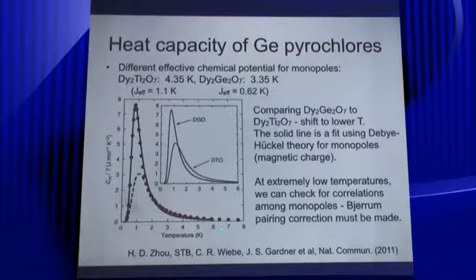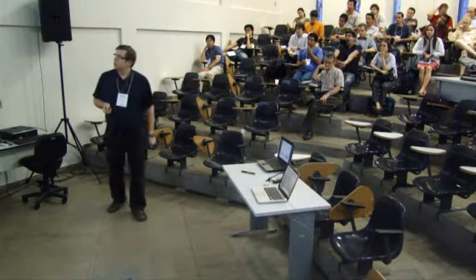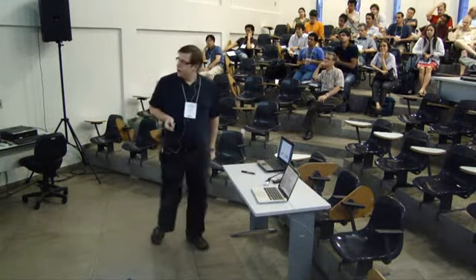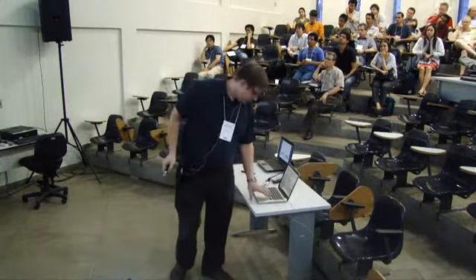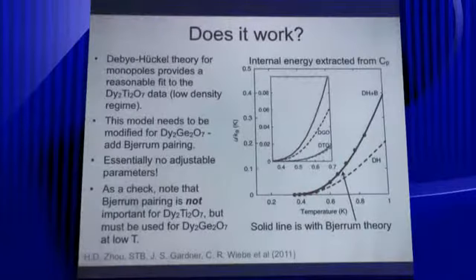And this is a fit that we've done to the Debye-Hückel theory with the chemical potential. So the chemical potential is smaller than you have for dysprosium titanate, which is the reason why you have many more monopoles at low temperatures. So what we decided to do was look at the heat capacity at lower temperatures, because as the monopole density becomes really high, you should have significant corrections for Bjerrum pairing at low temperatures. So this is showing you the internal energy we extracted from the heat capacity.